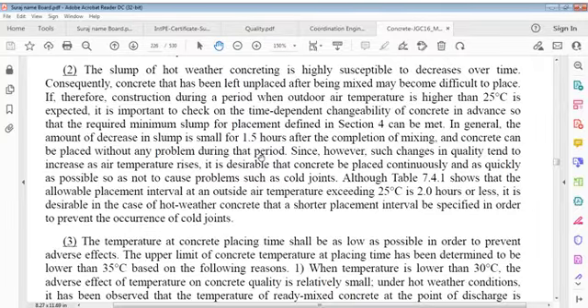Slump of hot weather concreting is highly susceptible to decrease over time. Consequently, concrete that has been left unplaced after being mixed may become difficult to place. If therefore a construction during a period when outdoor air temperature is higher than 25 degrees Celsius is expected, it is important to check on time dependent changeability of concrete in advance so that required minimum slump for placement can be met. In general, amount of decrease in slump is small for 1.5 hour after completion of mixing, and concrete can be placed without any problem during that period.